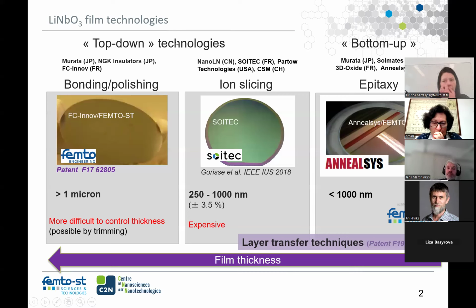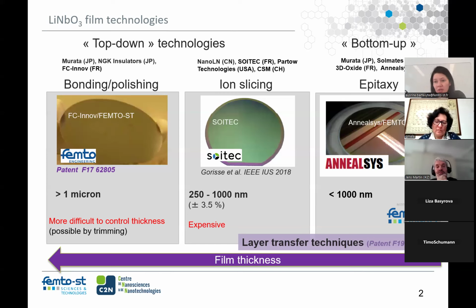Basically, we produce high quality single crystalline films by simply bonding, grinding and polishing down. That is a very good method to obtain, for example, 10 micron, 3 micron, 5 micron, or 1 micron thick lithium niobate films, bonded on any substrate. Right? It can be bonded on any substrate. We can obtain any orientation by simply bonding and polishing.